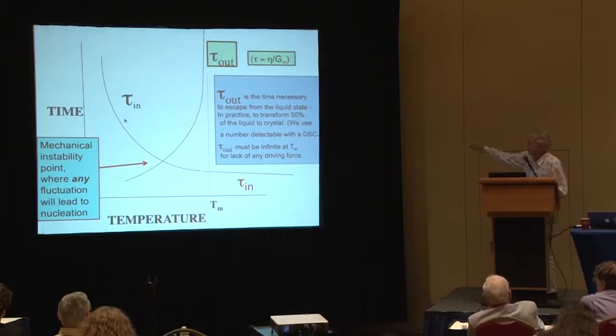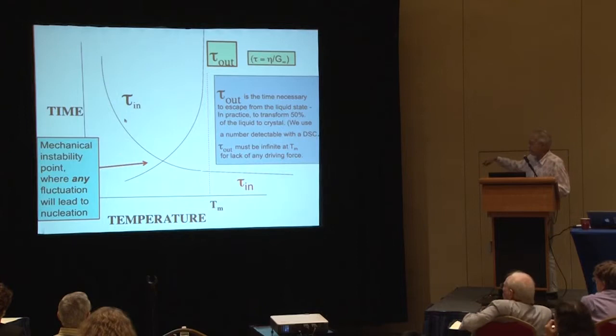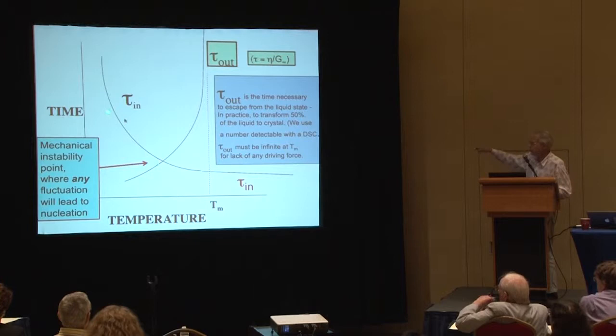So what I plotted here then are two time scales, one which is the one related to viscosity and diffusion, which is the time scale within the liquid, which is going to very long values as you approach the glassy state. And the other one is this, what I call tau out, which is related to the viscosity by the Maxwell relationship, which starts off at infinity at the melting point because there's no driving force to get the crystal at that point. And it gets shorter and shorter as the system gets more and more metastable, and the driving force for crystallization in free energy gap gets larger.